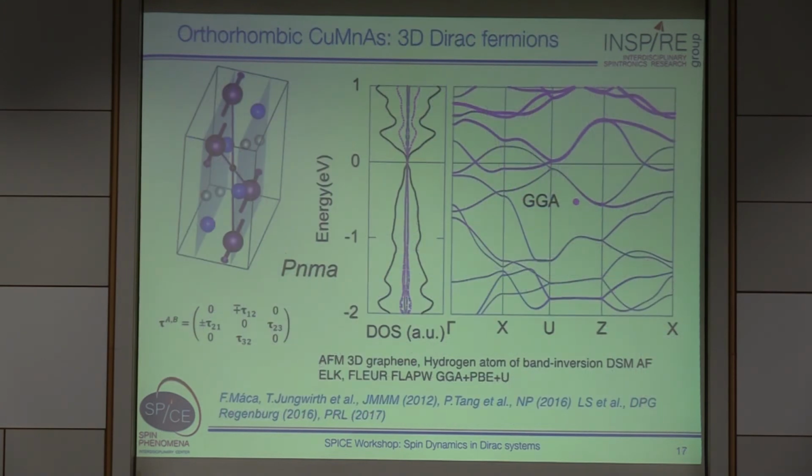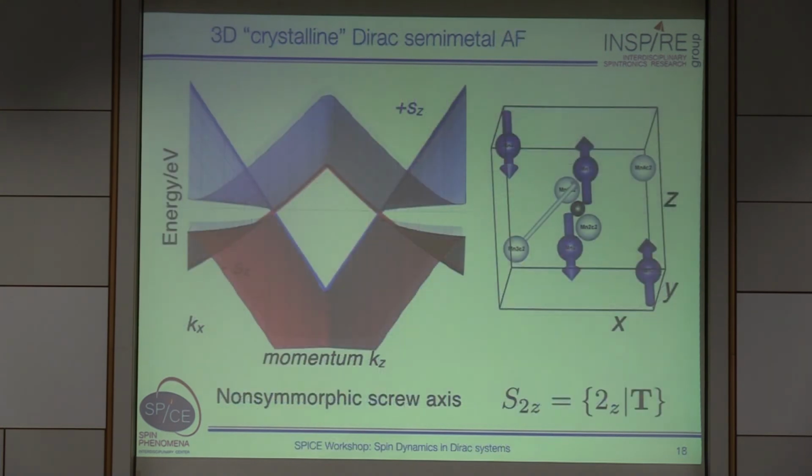But this is not enough, right? So we need to go for something at the Fermi energy. We can expect some transport manifestation directly in magnetoresistance, for instance. And well, this orthorhombic variant, which has a unit cell twice as large as the tetragonal one, is giving you exactly what you need. So you see that if you calculate the non-equilibrium spin polarizations, they follow the PT symmetry.